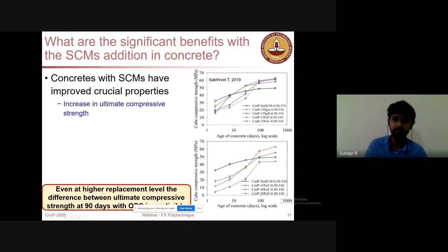But at the early stage, OPC will have much higher strength than these cements. But we shouldn't judge it with 28-day strength. So you should be aware of that. When you use concrete with SCMs, you shouldn't judge by taking the measurement at 28 days. You should at least give some time and then see whether you have enough strength. At 90 days, you could see some of the mixes performing better than OPC.